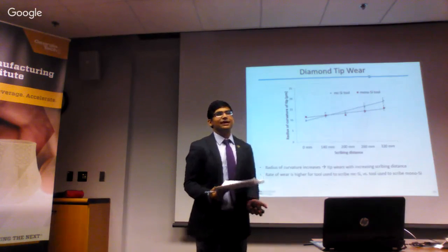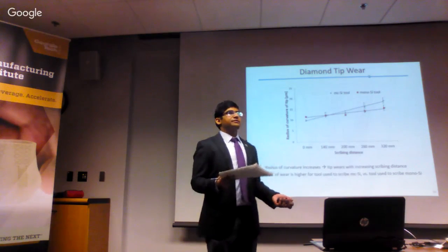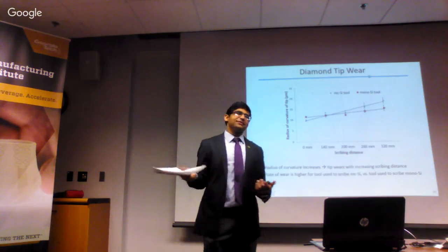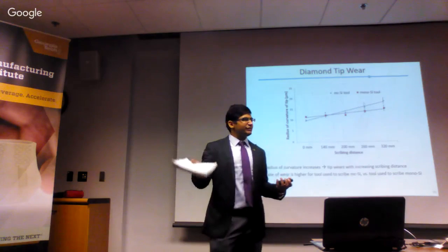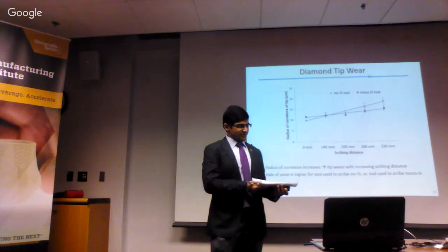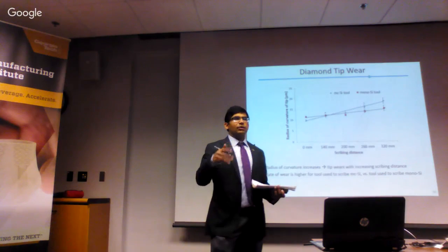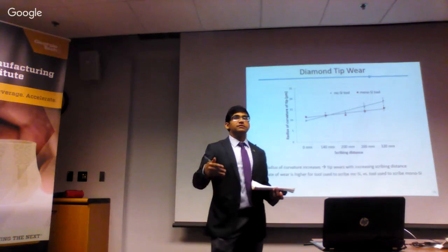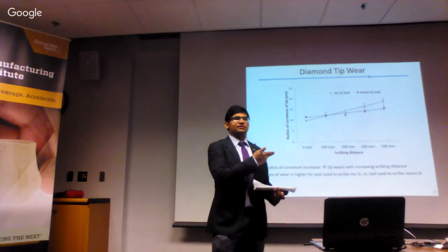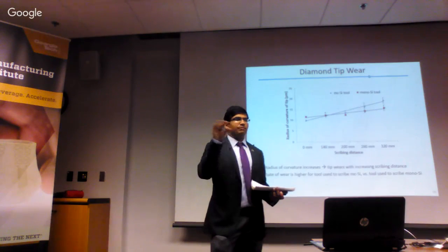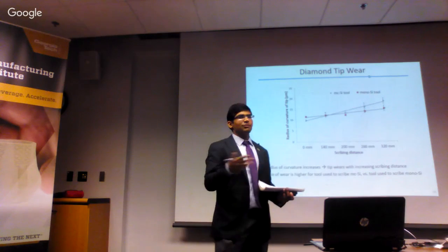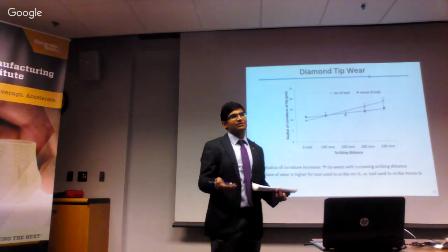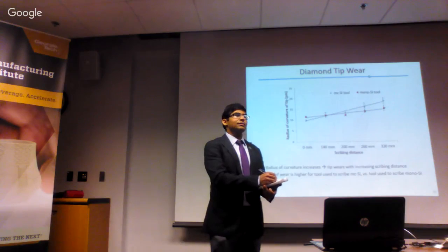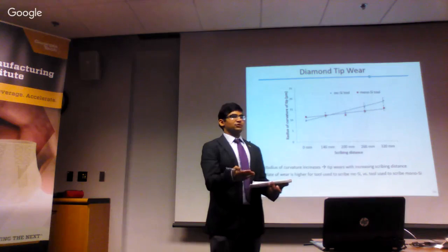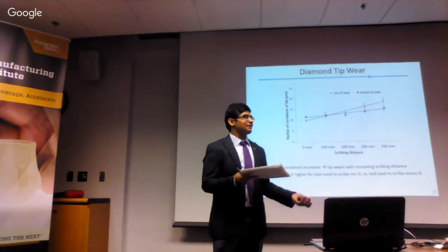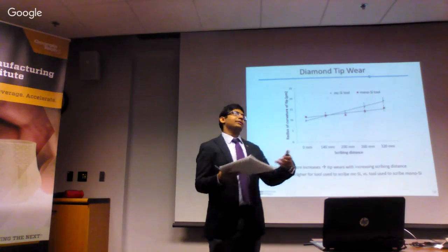So I acknowledge the fact that I'm doing very low speed scribing experiments, and there would be an effect of speed, which is one part of the proposed future work. In the actual wire sawing process, it's moving at 10 to 15 meters per second, and I'm moving at less than 1/10 of that. Huge difference, and we know in cutting operations, the speed would affect the amount of energy going into the process, and might affect temperature. Here we're only talking about stresses, and I did not talk about temperature at all, because I found using empirical models the temperature increase is not high, not more than 100 degrees Celsius, which would not create any change on diamond. But with dynamics, I am expecting there will be more effect of temperature and other things, which will create more wear. But that would affect both mono and multi equally. So the results here still would hold, but we have to take dynamics into account.